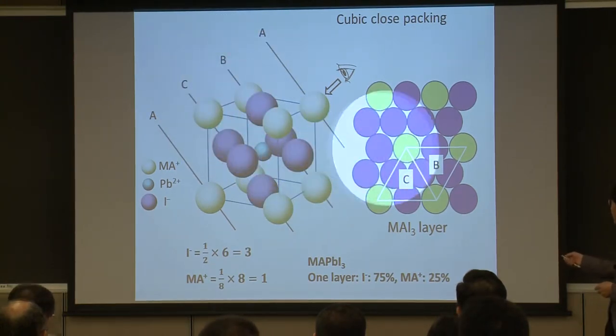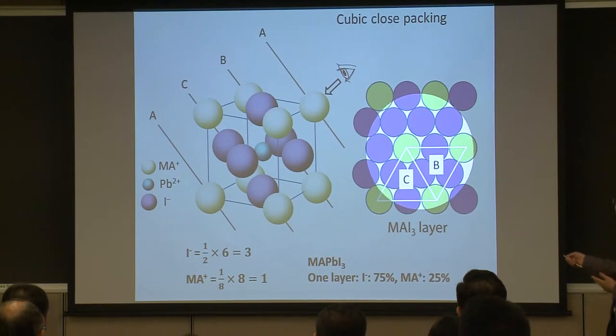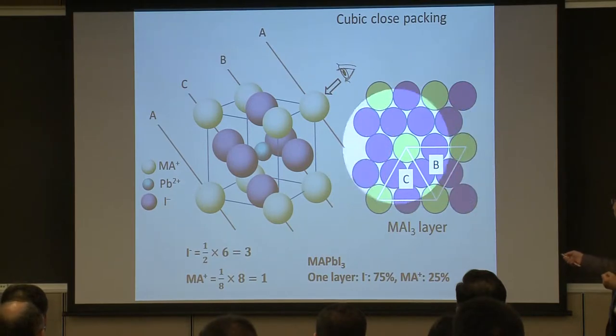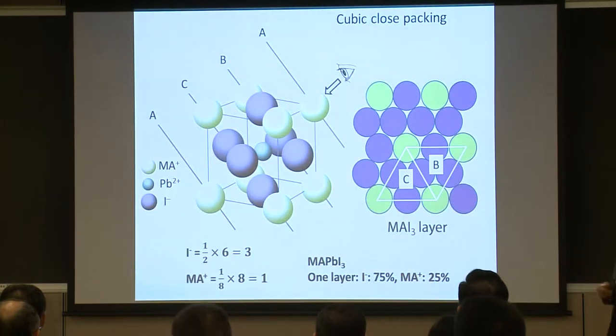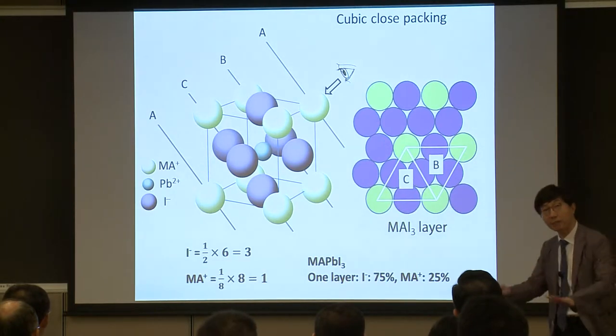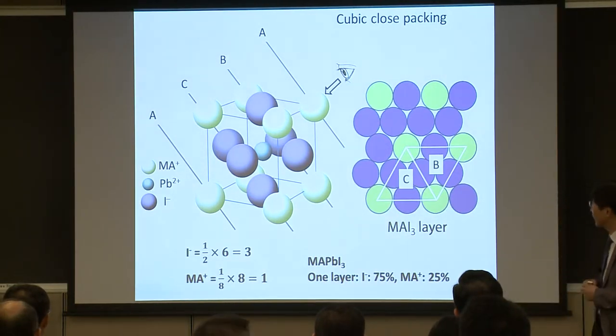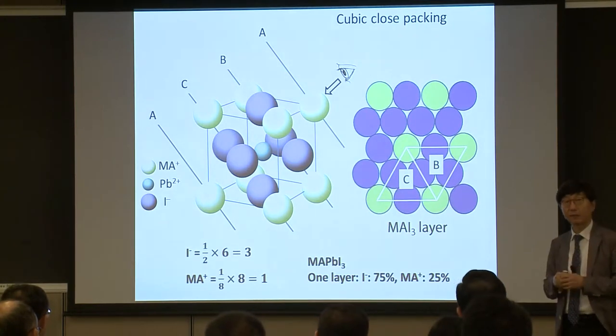If you take one layer, such as the B layer, it looks like this, where the green color is the A-site cation and the purple color is the X anion. The green is surrounded hexagonally by the iodide anion. So 75% iodide and 25% A-site cation sit on the same plane. And if you have some missing element, such as iodide or cation, then you have a defect.